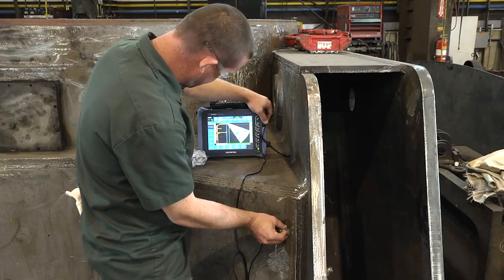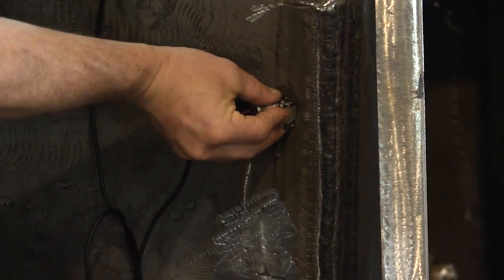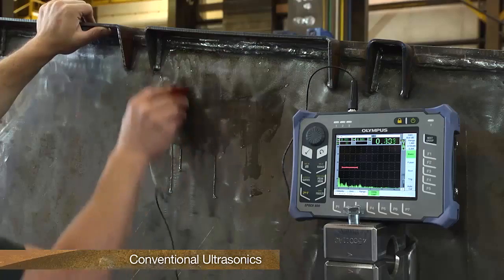We do have some parts that we had to draw out in a CAD model and figure out which angle is the best. For one part, for example, we found out that a 55-degree angle was the right angle needed for that part to find the crack. With phased-array, we can pretty much eliminate buying that 55-degree wedge and just use our regular transducer and wedge on that.